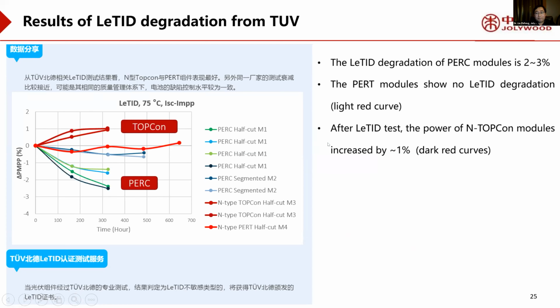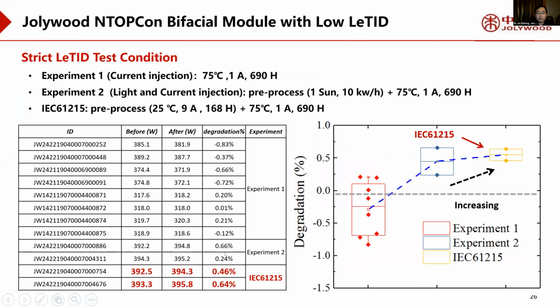So according to this data, we can find that for the N-type, no matter N-PERT or TOPCon, the LeTID is very much lower than PERC. And this is some data from our Jolywood lab. We can find that the LeTID is also less than 1%, just 0.5% after the LeTID test.